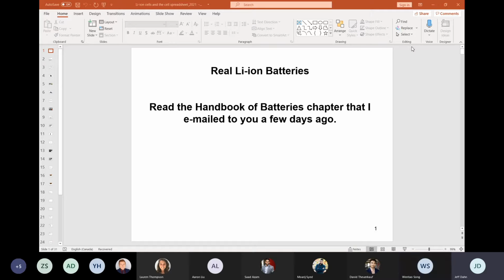So with LiMn2O4, if you add lithium to that, it will go in at about 2.8 volts and come out around 4 volts. If you take Li4/3 Ti5/3 O4 and try to remove lithium, it won't come out within the accessible voltage range. So it's a different story because you're adding from half filled, if you like. The voltage is still a lot lower than the other ones.